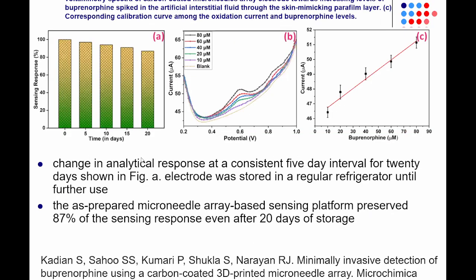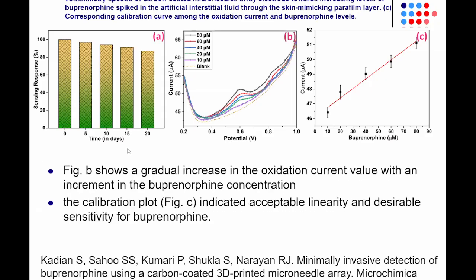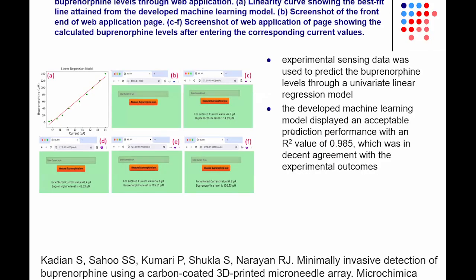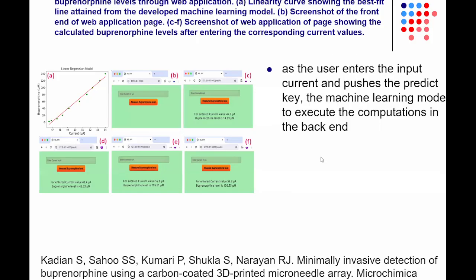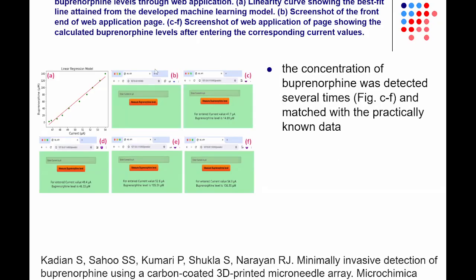Here you can see that the performance of the sensor was preserved at a level of 87% after 20 days in storage. So we also see here the calibration plot has relatively good linearity and good sensitivity. Our linear regression model, as before, showed in this case also a high R-squared value of 0.98. Again, we put in the current, and you then have machine learning to provide us with the concentration, and the concentration and current match the known data.